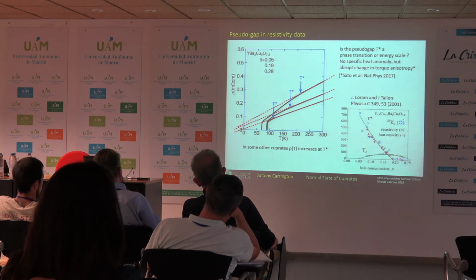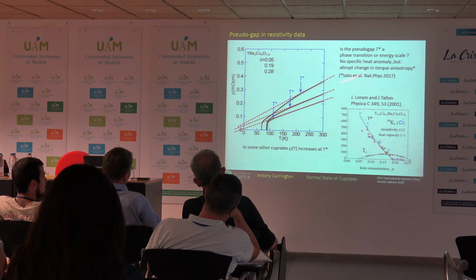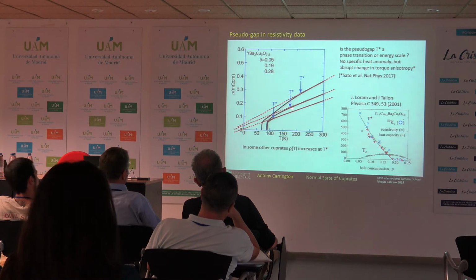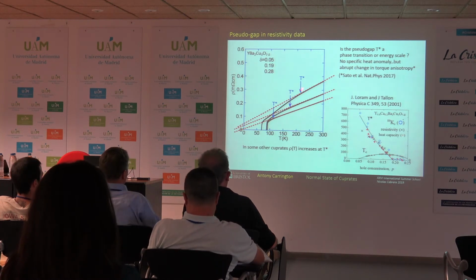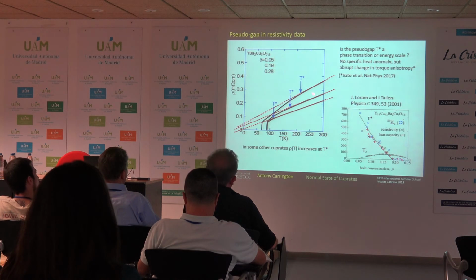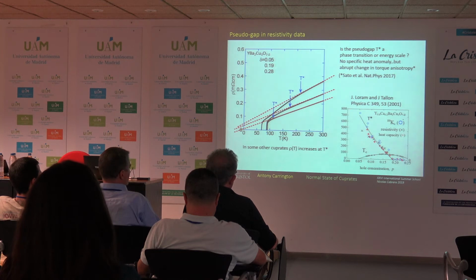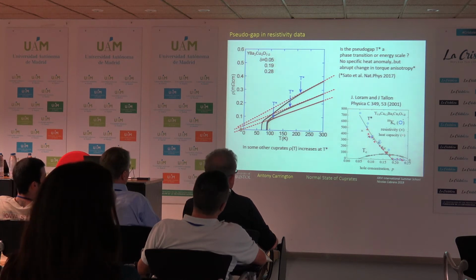Okay, so there's some controversy as to whether or not when you get to this point here, T star, so basically just to run you through this, you've got the resistivity, optimal doping, it's linear, and then as we take oxygen out, it's still linear at high temperature, and then at some point it breaks away from it, and we call that T star. Okay, and it turns out that this T star here is an energy scale which is replicated in lots of different experiments.